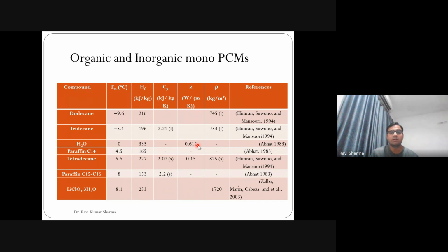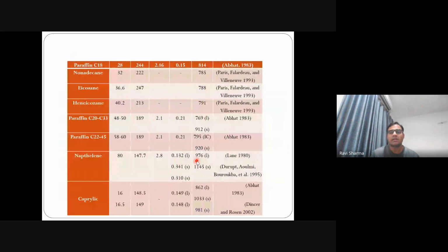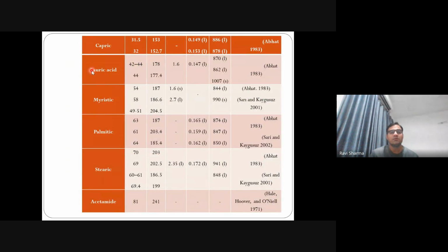The water is an inorganic material, the conductivity is 0.6. Tetradecane is an organic material, the conductivity is 0.15. So the conductivity of all organic materials is very low. Paraffin 0.2, naphthalene very low again, caprylic acid very low again, and all of these are organic materials. You can see their conductivity is very low.